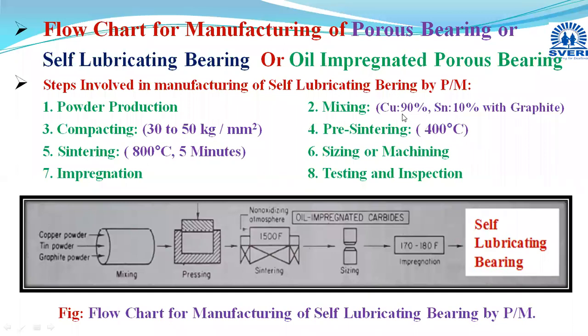Means this copper and tin particles, or copper and copper particles, they will form a bond. Okay, or addition will occur due to the pressing, and the strength of that component will get improved. Then sometimes, due to proper pressing, some plastic deformation may occur in the powder particles, and this plastic deformation will help in the sintering stage. So after completing this compacting process, the component obtained is termed as compact or green compact, and it is subjected to the next stage, that is sintering.